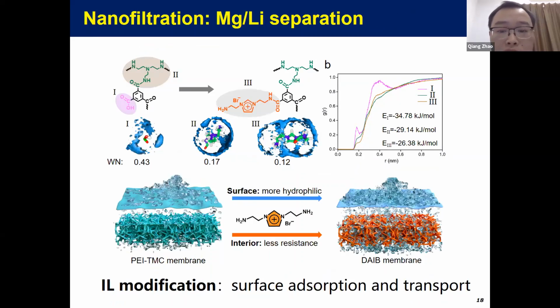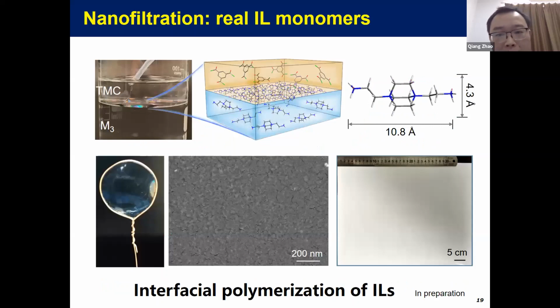And we also go into details of the separation mechanism of this new membrane for magnesium separation. We did simulation and characterizations to test both the surface and the internal, the bulk part of the membrane. And we found that the membrane surface has a hydrophilic property, while if you go deep inside, it has sort of less hydrophilicity. That is, both the adsorption and the diffusion were accelerated because of the surface modification, which leads to high membrane permeance. With this in mind, we also have a couple of works which are still in preparation.